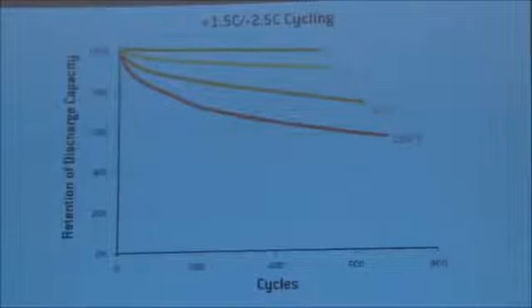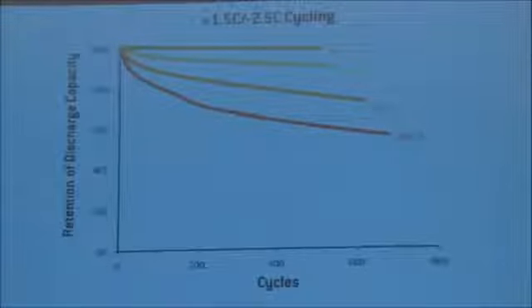And how are these batteries tested? Well, this 1.5 C means it was charged in about 40 minutes. And this minus 2.5 C means it was discharged in about 20 minutes. So each charge-discharge cycle takes about an hour or maybe a little more. So this entire test took about 500 hours or so. This experiment was done very rapidly, in a little less than a month.